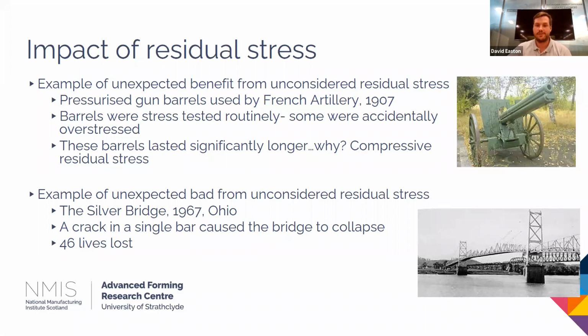Similarly, if you fail to account for residual stresses, then catastrophic failures can occur, unfortunately. The Silver Bridge in Ohio, a single crack led to that crack propagating due to residual stresses, and many people died, which just highlights the importance for understanding residual stresses and then hopefully reducing them to a level that enables safe operation.